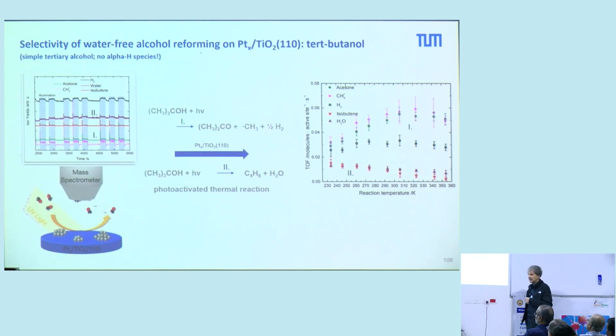Now the question is tertiary alcohols. I showed you that in our mechanism, in the aldehyde formation, we always split the CH bond in alpha position. In tertiary alcohols, we don't have an H in the alpha position. What happens? Here you see the results of tert-butanol, and you see that again we can explain the results with our mechanism. You see the acetone formation, but here you don't produce any hydrogen, but you produce the CH3 radical that we detected with mass spectrometry. That means again we have exactly the same mechanism that we proposed. At low temperature, you also have the photoactivated thermal reaction producing isobutene. But the main product is exactly according to our mechanism.